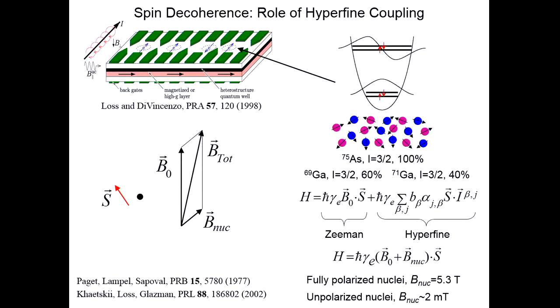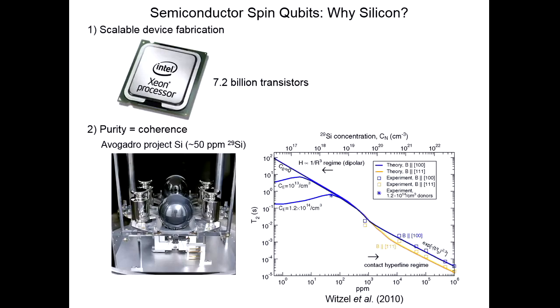So there are a couple of ways to deal with this. One is to try to polarize the lattice nuclei so that they're not fluctuating, and Amir Yacobi's group and other groups have looked into that. The approach that we're taking is just to jump ship, leave III-Vs behind and move to a different material system. And the material system that we selected, and I think the community at large is kind of headed in this direction, is silicon. One reason is just mass production works well with silicon devices, and so if we can make a few qubits work well, the hope is that this is a technology that could quickly blow up into a much larger system size.